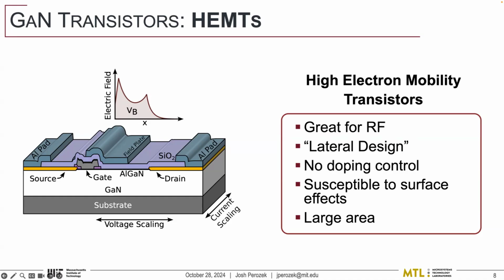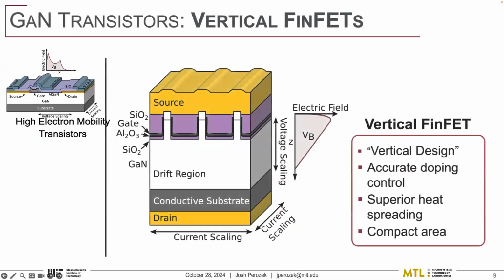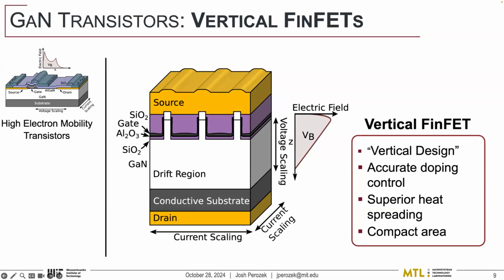In contrast to this, what we focus on here at MIT and we've really developed and pioneered is the vertical GaN FinFET, which is a vertical architecture. This is a switch that silicon and silicon carbide have done for as long as they've been power devices. The idea is that instead of making a larger device to scale the voltage, you make a thicker device. Our voltage now scales in a third dimension, which lets us keep everything very compact. And we can now scale the current just by having a larger area device. It's a 1-to-1 ratio there.